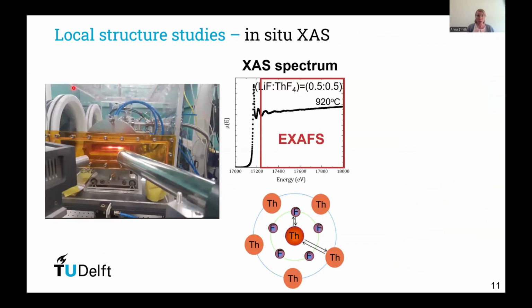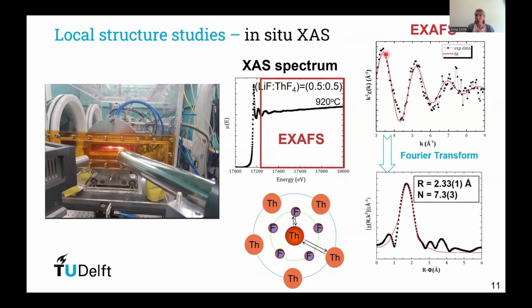Here is a picture of our furnace setup at high temperature with some detectors in front. And so again, this EXAFS region. After some mathematical treatment of the data, we get the EXAFS signal, and after Fourier transform, we get this figure, which is a bit equivalent to a pair distribution function, where thorium is here, and we see here the first coordination shell of fluorine around the thorium-absorbing atom. So when we fit this data, we get some average information on the local structure.